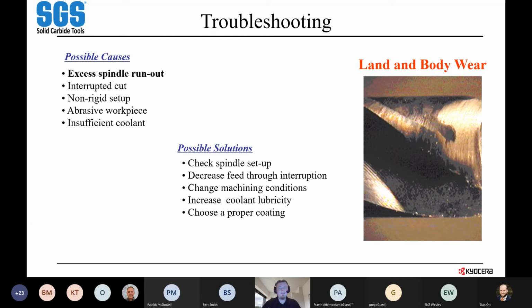Land and body wear. Usually this is a spindle runout issue. Not always, but usually it is. And you'll see it in irregular patterns across the body of the tool. So one side of the tool is rubbing more than the other is, so you'll see those wear patterns. It can be caused from an interrupted cut, the setup not being rigid, as well as if you have an abrasive material like a casting or something like that that has impurities or potentially even voids in it. And then, of course, like everything else, insufficient coolant can cause issues like this as well.